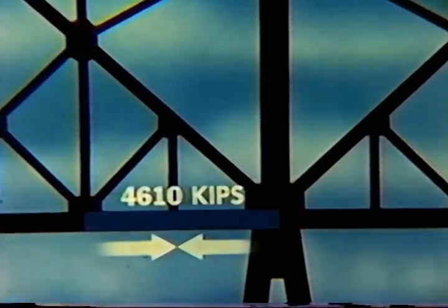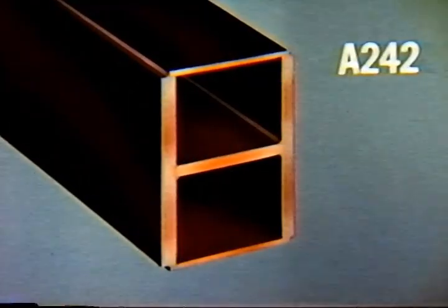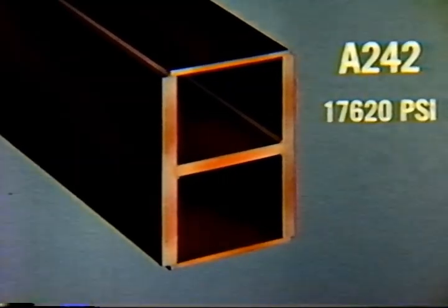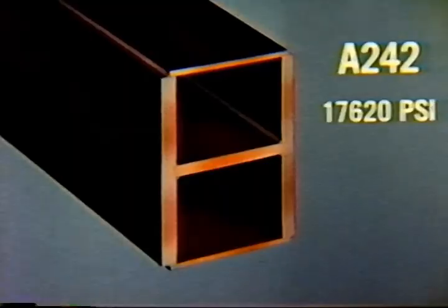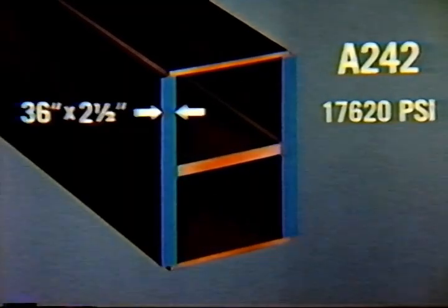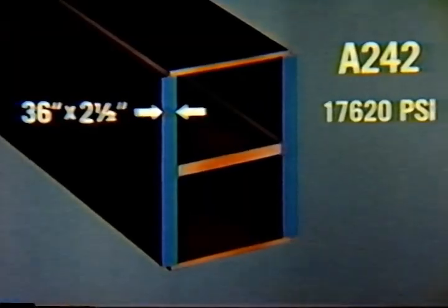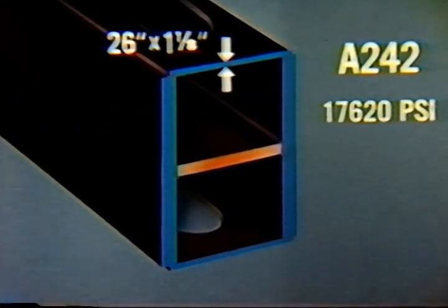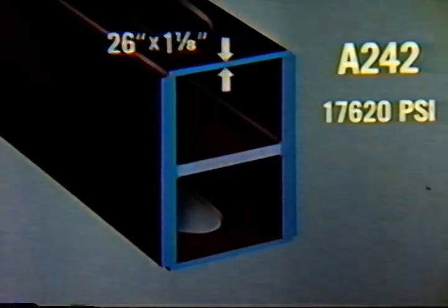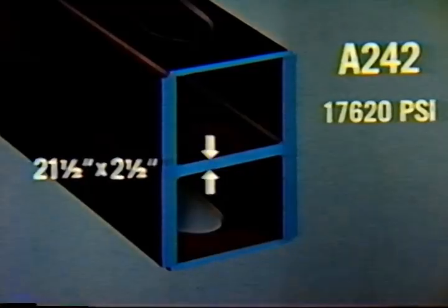This highly stressed lower chord member, for example, will carry a compressive load of approximately 4.5 million pounds, 4,610 kips to be exact. Use of A242 type steel at an allowable stress in compression of 17,620 pounds per square inch would require a reinforced box section with two plates 36 by 2½ inches, two perforated plates 26 by 1 1/8 inches, and one plate 21 1/2 by 2 1/2 inches, weighing 955 pounds per foot, or 53,000 pounds for the member.